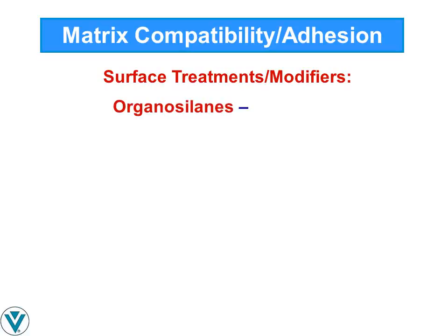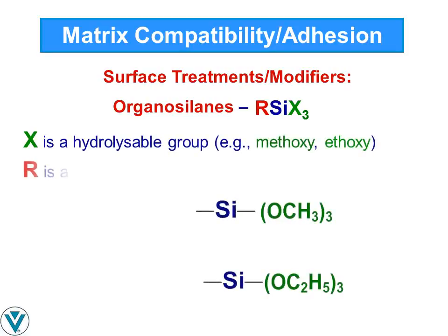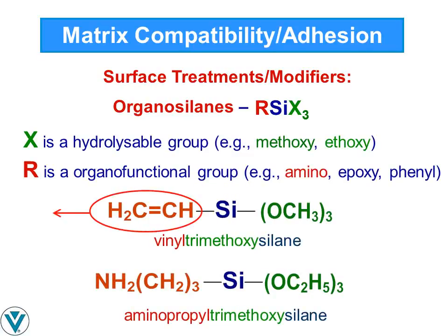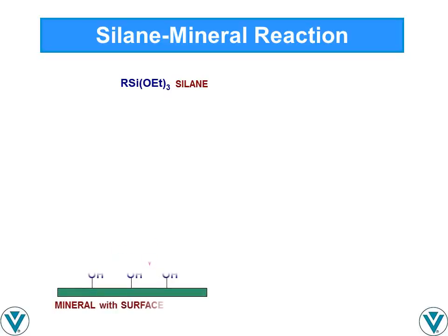The general chemical structure of organosilanes is R-SiX3, where X is a hydrolyzable group, such as methoxy or ethoxy, and R is a non-hydrolyzable organofunctional group. The organo group may be reactive toward the polymer matrix, or it may be unreactive and serve as a hydrophobe or wetting agent. Modification with organosilane depends on the ability to form a bond with silanol groups on the silicate mineral surface. Since the silicates that are successfully silane modified generally lack structural silanols, these are a result of the reaction of silica surfaces and adsorbed atmospheric moisture.